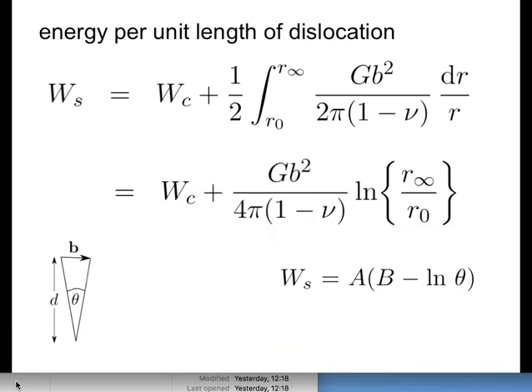Yeah, so what you have is an equation in which you have log of R infinity over R naught, and the form of that equation we'll simplify to just a constant A minus a constant B times log of theta, because from this equation, if I set R infinity as d, the spacing of dislocations in the array, then d and theta are inversely proportional. So we can replace R infinity with 1 upon theta, and that's why we have this minus sign in front of the log. Okay? So you have the dislocation energy per unit length varying with log of the misorientation angle theta. Okay? Is everyone happy with that?